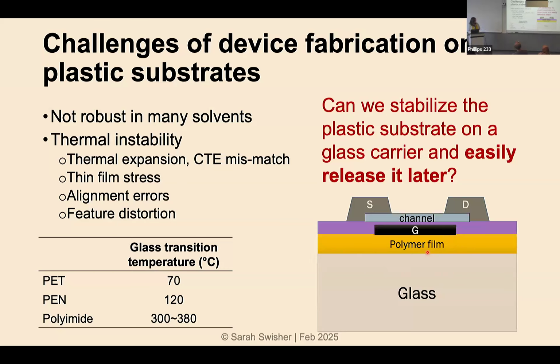And I don't want to have a structure that looks like this, where if I were to shine light through the back of this glass, I don't want to rely on absorption in the polymer, and I don't really want to only heat here. So what we did is we introduced this light absorber layer. So it's just a metal coating on a glass substrate. And on top of that, we spin our polyimide and fabricate our devices.